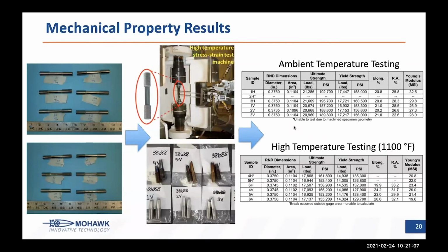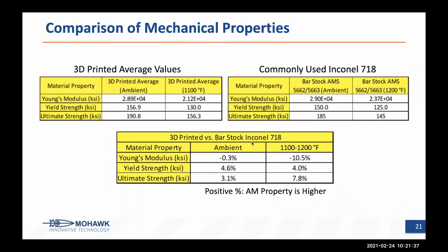So we took the round bar specimens, machined them into dog bone specimens that can be put into an Instron machine to do the tensile testing. And it was done at both room temperature and near the operating temperature that we would expect to see, or 1100 degrees Fahrenheit. The table on the right shows the type, the samples, and the data that was acquired. But the details I'll show in the next slide here.